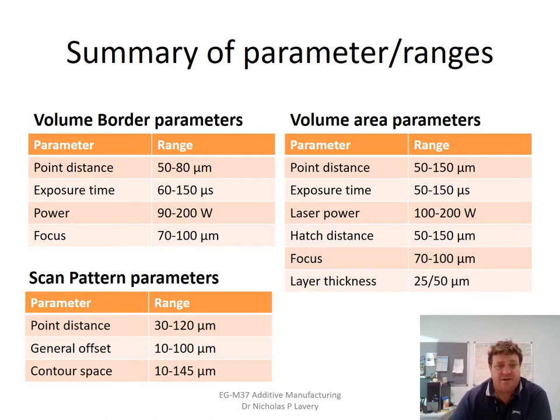Now let's have a quick look at these and summarize these parameter ranges. So for the point distance, which is the space between one laser firing and the next, it's typically somewhere between 50 and 80 micron. At each point, the laser is kept on for a very small period of time, 60 to 150 microseconds. The power will vary somewhere between 90 and 200 watts, and the focus will be somewhere between 70 and 100 micron. So it's pretty typical value ranges.